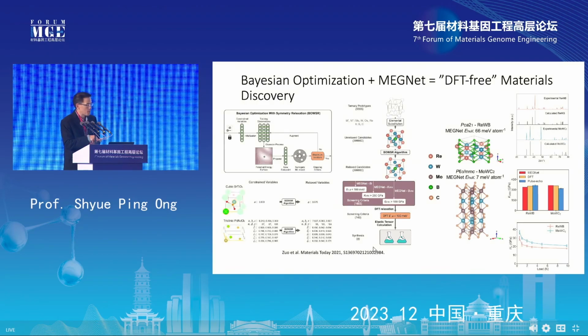And finally, our experimental collaborator actually went ahead to make it in the lab, okay? And I'm showing you just 2 examples of the materials that they found. So there's this rhenium tungsten boride and this moly tungsten carbide. They are both completely new materials. In other words, these are materials that no one has ever reported before. The measured XRD patterns are very, very close to what we predict from our computations, and the properties are also extremely close to what is predicted from our machine learning models as well as our DFT calculations, okay? So this work was done by Yunxing Zuo, who is actually in the audience today, okay?